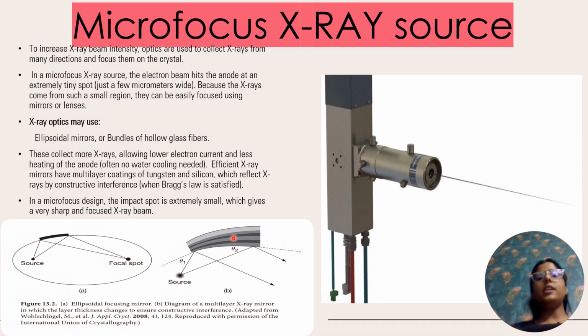This enhances the reflection at certain angles, improving the mirror efficiency. As the mirror is curved, the incidence angle changes along its surface, so the layer thickness is gradually varied. Thicker layers where theta is smaller, thinner where theta is larger, ensuring that Bragg's law is satisfied everywhere.